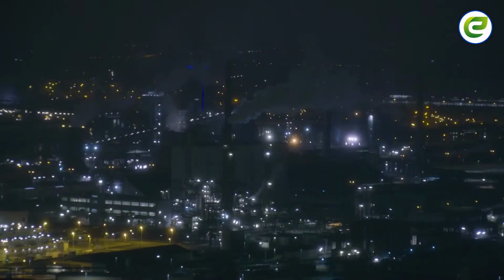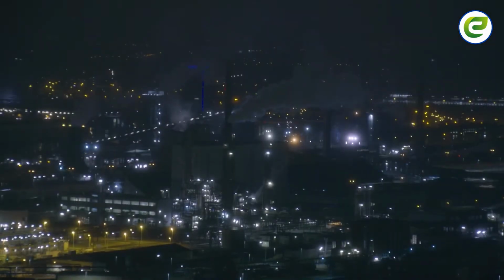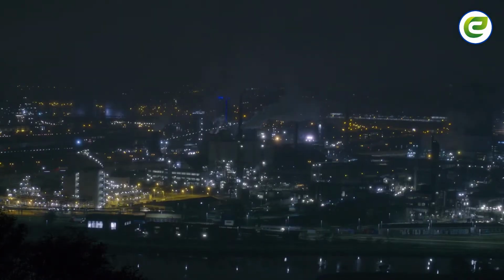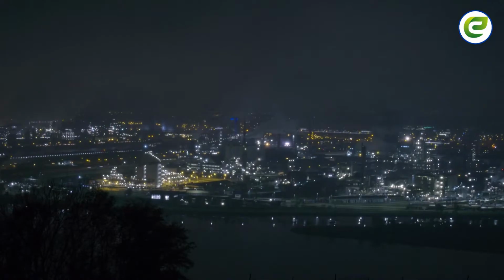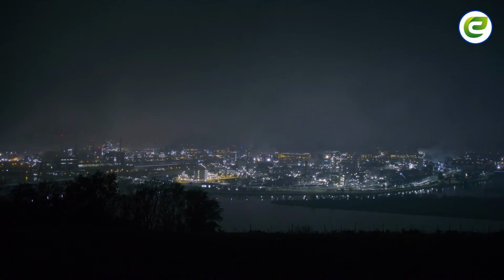In addition, by adding lime to the charge, it was possible to produce a basic slag that would remove phosphorus and sulfur. With this process, which became known as the basic oxygen process, BOP, it was possible to produce 200 tons of steel from a charge consisting of up to 35% scrap in a tap-to-tap time of 60 minutes.